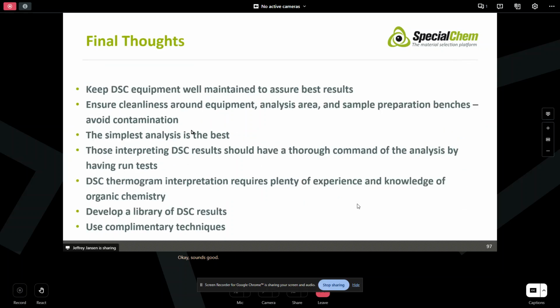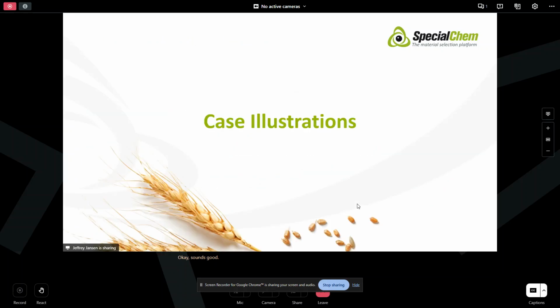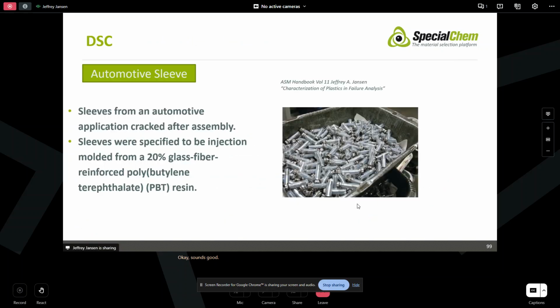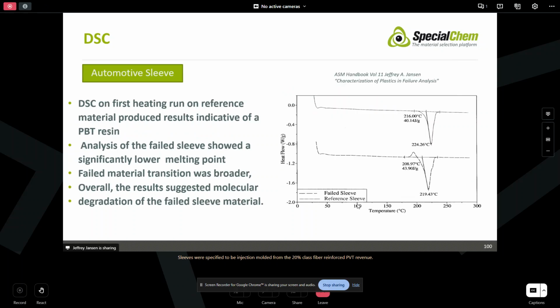Okay, sounds good. So here we had some sleeves from an automotive application that cracked after assembly. Sleeves were specified to be injection molded from a 20% glass fiber reinforced PBT resin. DSC on the first heating run on the reference material produced results characteristic of PBT. We had a melting point of around 224 degrees C. That looks good. Analysis of the failed sleeve showed a significantly lower melting point, 219.